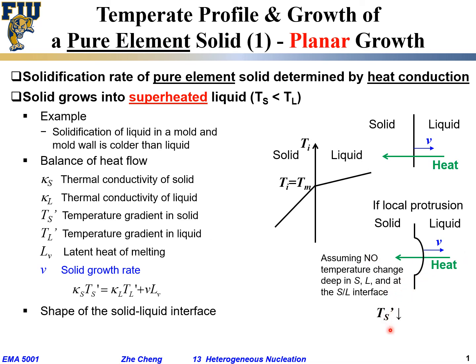Because of this, you would find, comparing the bottom situation with the top situation, our T'_S, meaning the temperature gradient in the solid phase, would decrease. Why? Because the temperature deep in here is the same. The temperature at the interface is the same, T_M, while the distance from here to here gets larger in this local protrusion. The distance got larger, the delta T is the same. As a result, the temperature gradient, the T'_S, decreases.